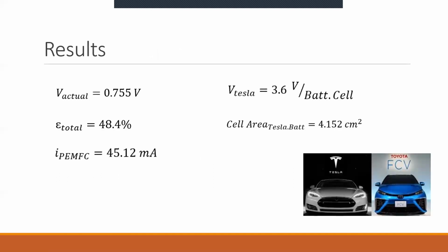The values we obtain from our theoretical fuel cell vary a bit from what a typical PEMFC should produce. A typical fuel cell usually produces an actual voltage within a range of 0.4 to 0.7 volts. Ours produced 0.755 volts, which is slightly higher than the typical. The efficiency of our system is within the range of a typical PEMFC though.